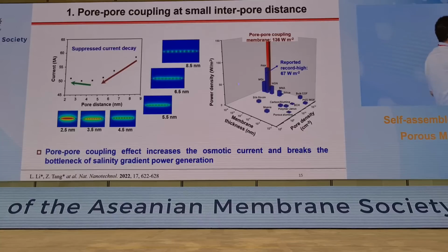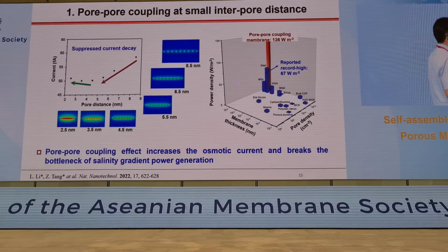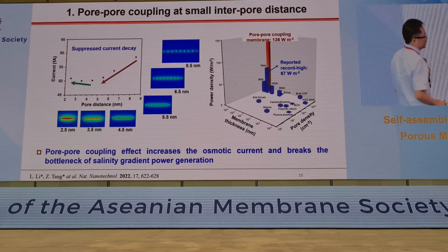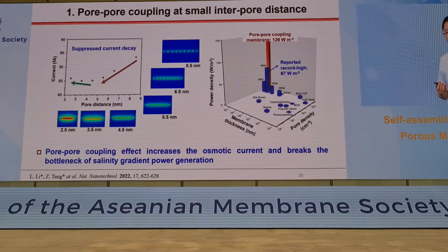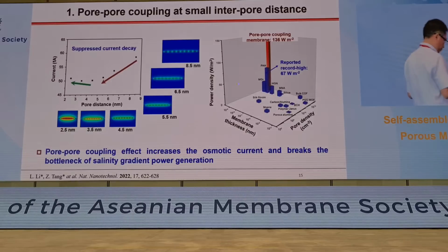As a result, we actually obtained the record high output power density of 136 watts per square meter, which is much larger than the previously reported result.